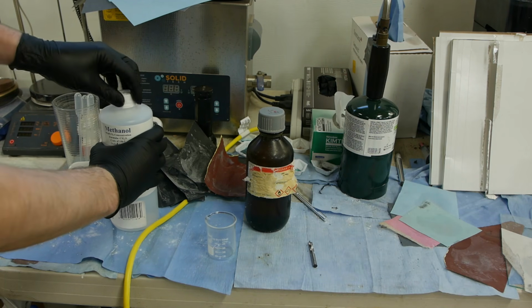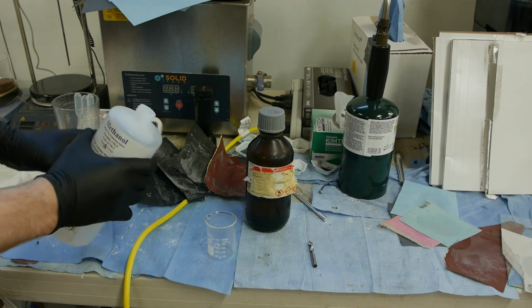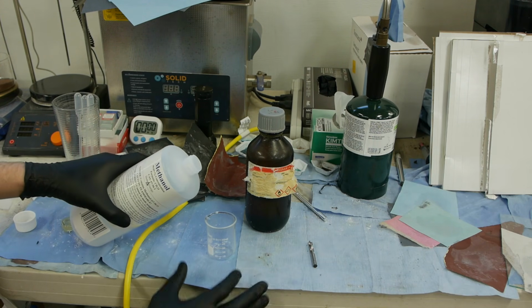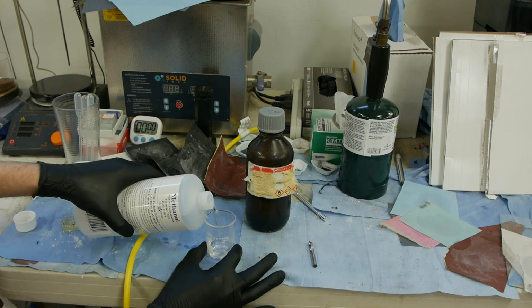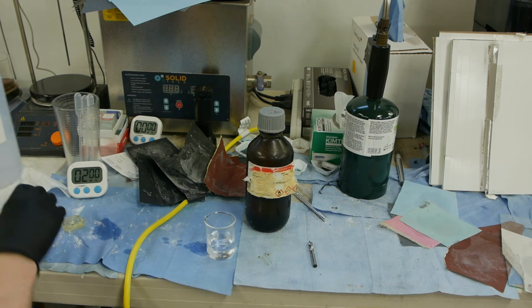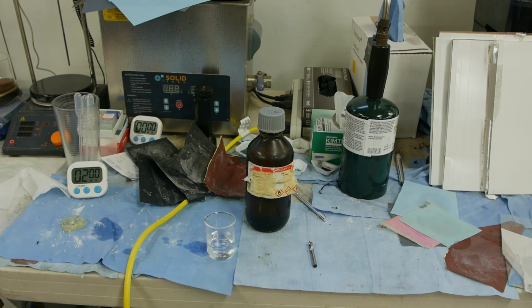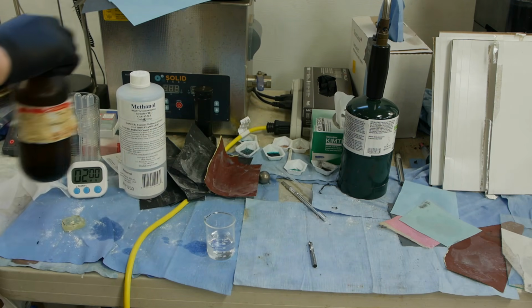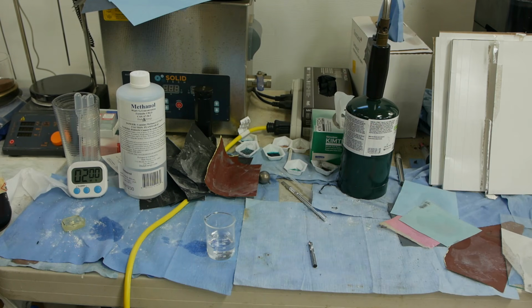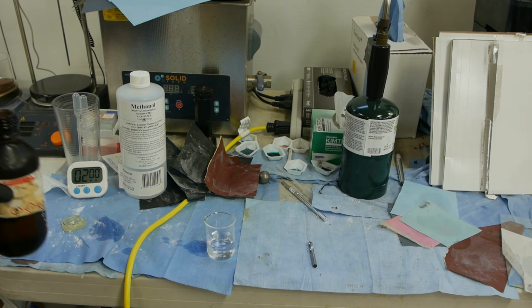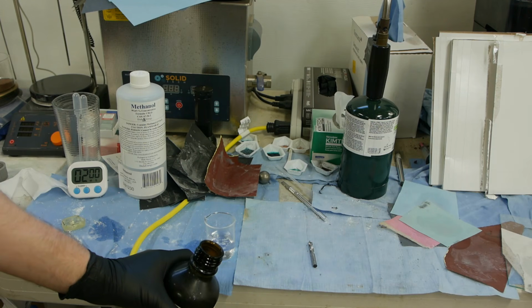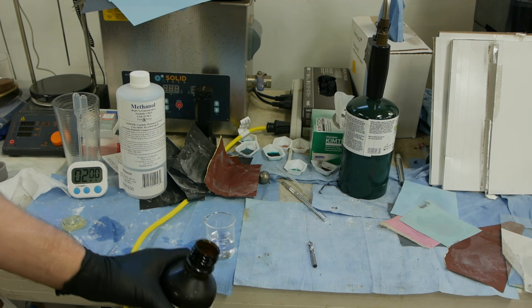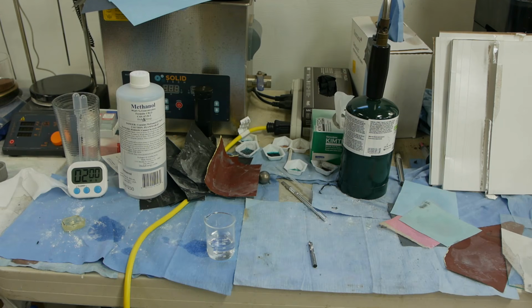The special etchant that I'm using is called Nital, for nitric acid and alcohol, and it's made by starting off with methanol or ethanol and adding to it about 5% by mass nitric acid. And this one is actually fairly dangerous. Nitric acid is a strong oxidizer, and you're basically adding it right to a bunch of fuel, the alcohol. So it's very important that we don't exceed 5% by weight nitric acid. There are some confirmed stories on the internet of really bad explosions that happened, I guess because someone capped the bottle and it outgassed, or maybe the thing just exploded outright. But anyway, if you're mixing this up, be very aware that this is in fact a potentially explosive mixture.